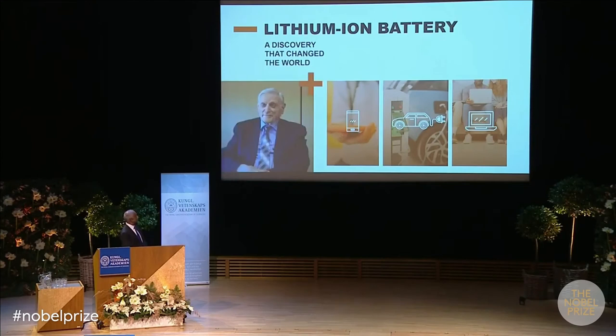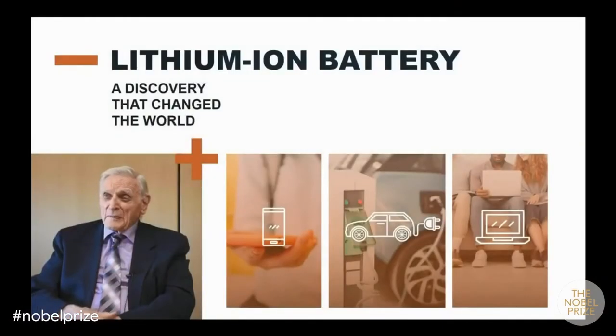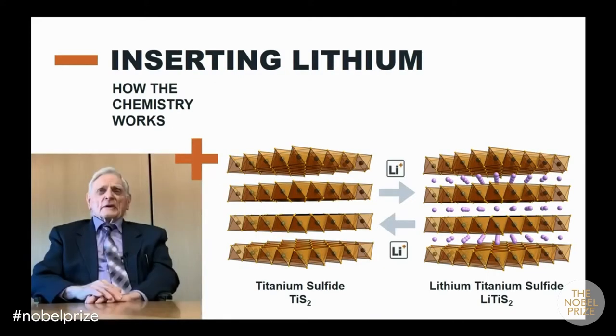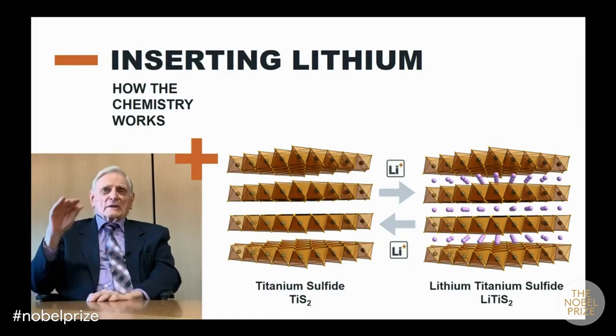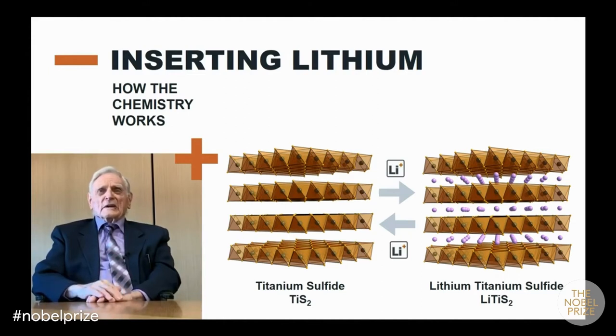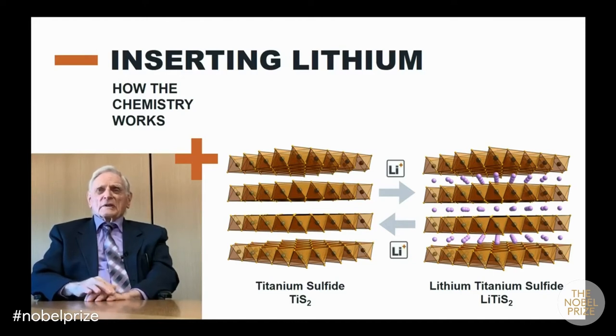Early 1970s, there was a problem of exposing the dependence of the Western world on imported oil. In the early days, people were reversibly inserting lithium between the MS2 layers of sulfides. So that was the idea. And when you insert between layers, it's called intercalation, meaning insertion between layers. And so they had TiS2, and the people were examining the chemistry of lithium insertion extraction from TiS2 back in the 1960s.